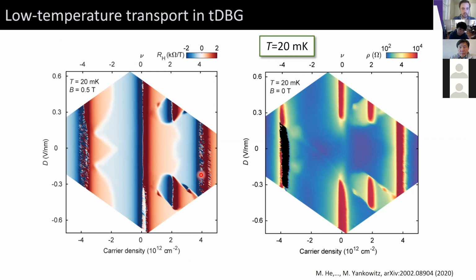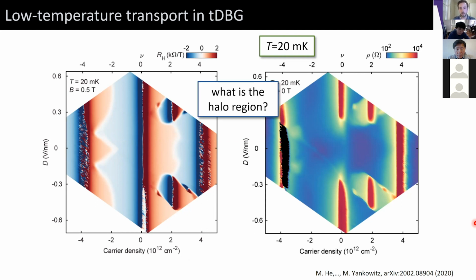bands. We see an additional sign change at partial filling of the conduction and valence band, which is necessary because the band is closed. So every electron that we initially fill into the system eventually has to be balanced out by some hole. But then we see that these halo-like features correspond to interesting regions where the sign of the Hall coefficient is actually opposite from what we would anticipate from a single particle model and what we see at displacement fields that are outside this halo region. And we see little replicas of these halos at quarter and 3/4 filling.